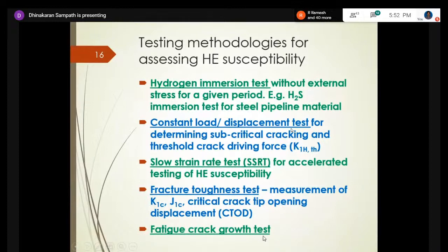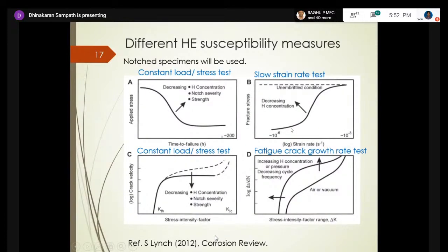So then the last one, if the component undergoes fatigue, cyclic loading in hydrogen, then fatigue crack growth is important. I'm going to show some susceptibility measures. So in different tests, what kind of information do we get? Most often in hydrogen embrittlement susceptibility evaluation, they use notched specimens, because the key thing is that hydrogen gets accumulated at the crack tip and that sustains crack growth.